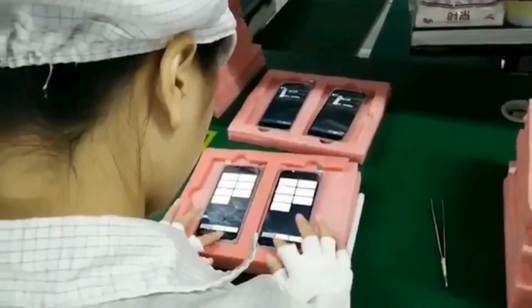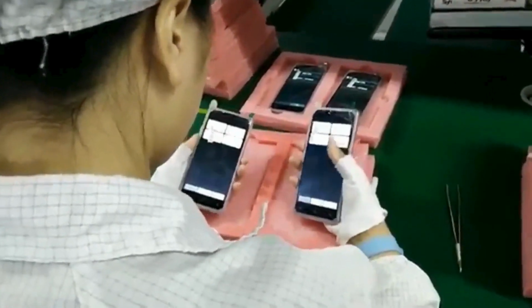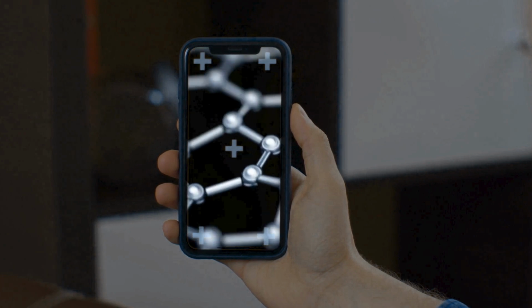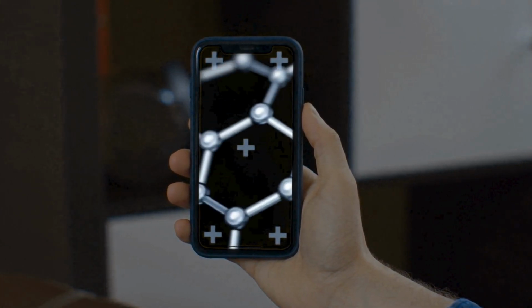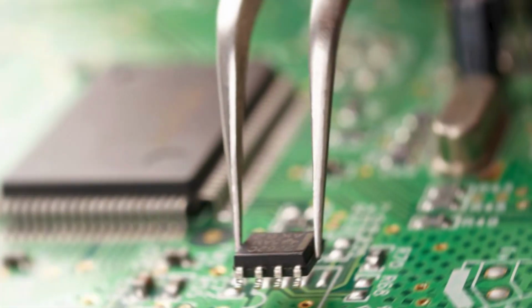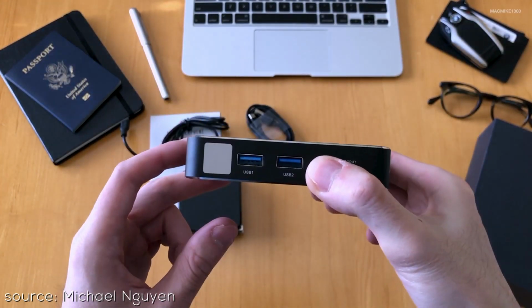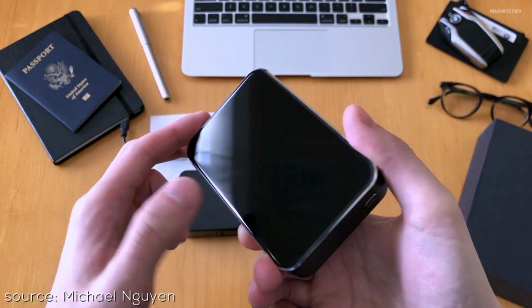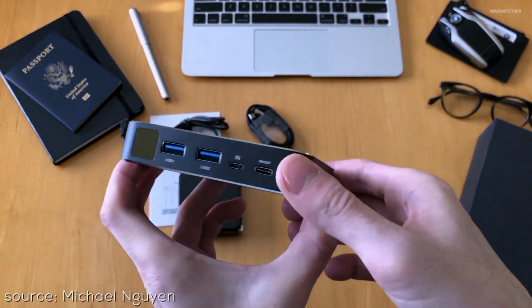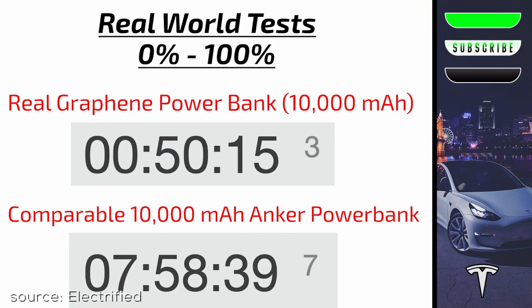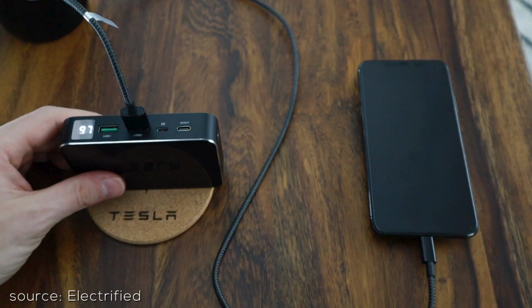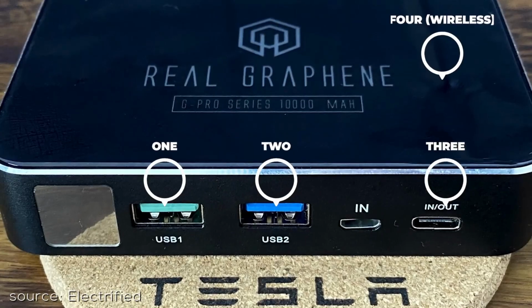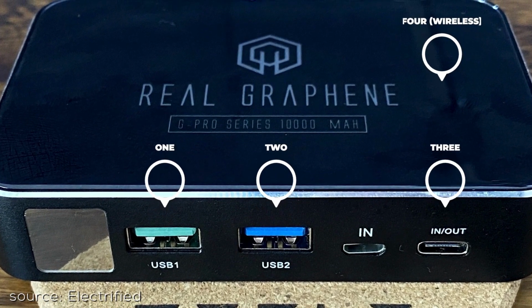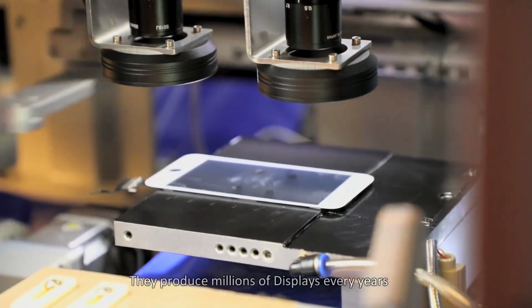Graphene's potential can also be seen via the creation of phone components. In particular, the material seems to have great potential in three distinct areas: the battery, the screen, and the semiconductor. Regarding the battery, one of the frontrunners is a company by the name of Real Graphene. That's because by creating a battery that mixed the lithium solution with graphene and introducing a composite layer of graphene, they were able to formulate it so that it could charge your phone in 20 minutes instead of the conventional 90. It would also last significantly longer than a regular lithium battery and generate less heat.